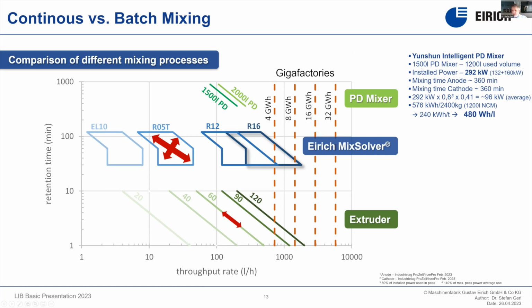A typical PD mixer with 1500 liter and 1200 liter has an installed power of almost 300 kilowatt with 6 hours mixing time. Having in mind that maybe just 80% of the maximum power is really used, and overall roughly 40% as a mean value, we have still an average of 96 kilowatt, which ends up as 480 watt-hours per liter. A double screw extruder roughly needs 100 to 160 watt-hour, which is quite significantly lower. And this gives you also the opportunity to save.